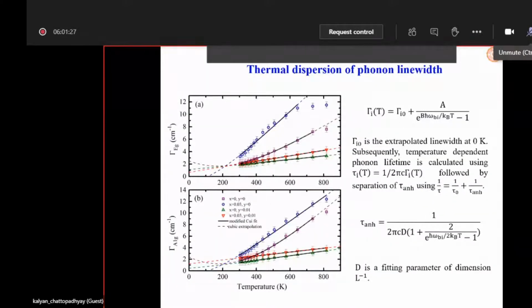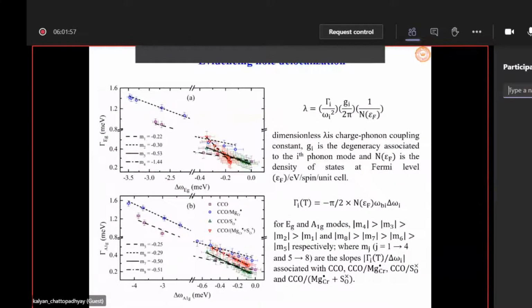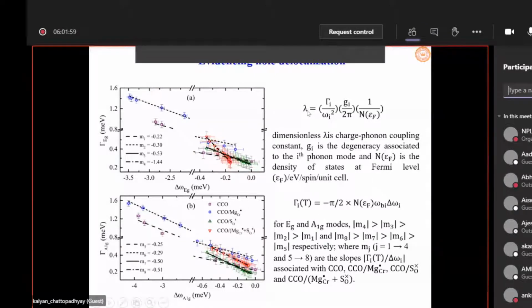Similarly, if you look carefully, the FWHM is also a strong function of temperature, and FWHM is related to the lifetime of the phonon. Okay, so similarly, we can fit this type of equation with temperature, and then extrapolate to find the value of FWHM at 0 Kelvin, which will be required for some of our calculations. Then, using the Allen formulation of the electron-phonon coupling constant lambda, it's very interesting that we can find the density of states at the Fermi level.